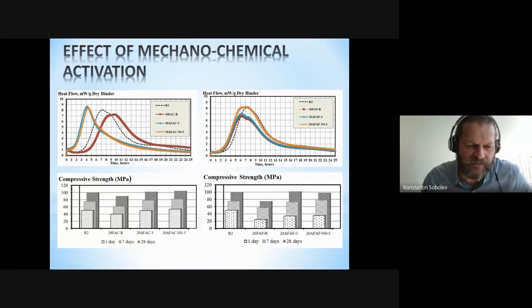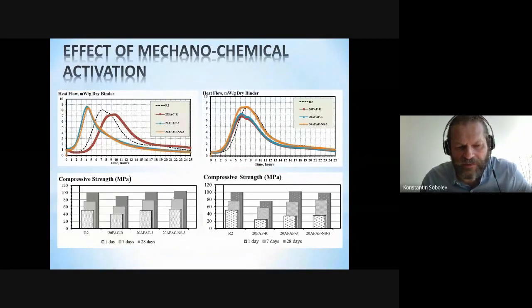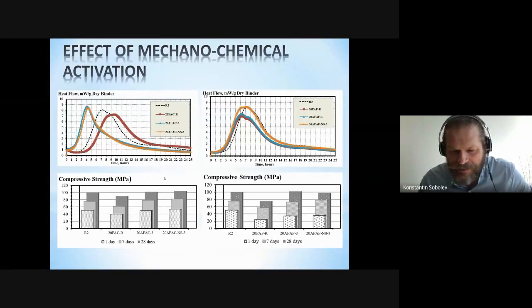As soon as we use an activated system, and specifically an activated system with nanosilica, it was demonstrating better strength than Portland cement. And again, the process of mechanochemical activation of fly ash is not complex. It's relatively easy to realize, and it has this potential benefit of converting class C fly ash into a material which is improving strength development of Portland cement systems. And yes, all these tests were done at the same water to cement ratio, so we don't have any effect of water to cement ratio.